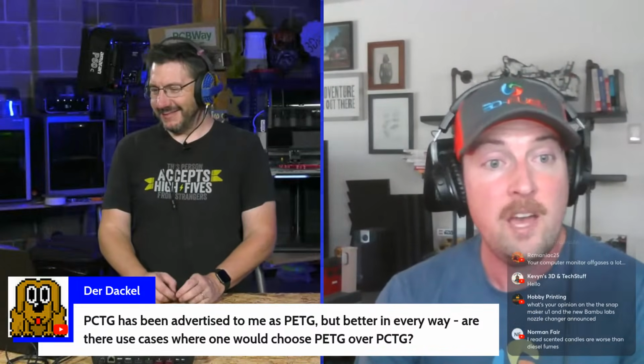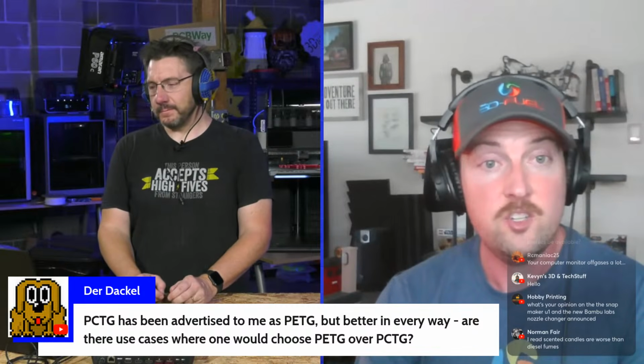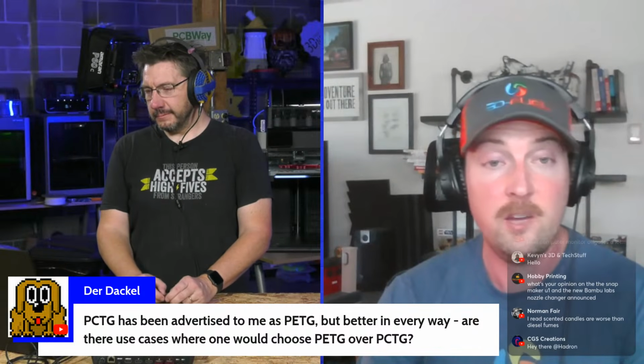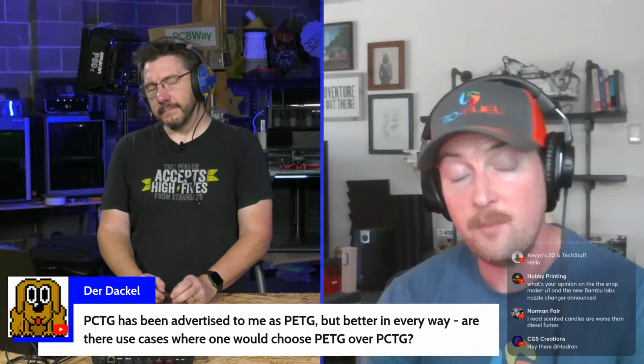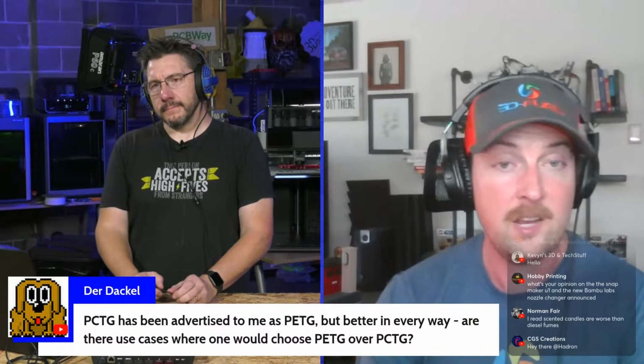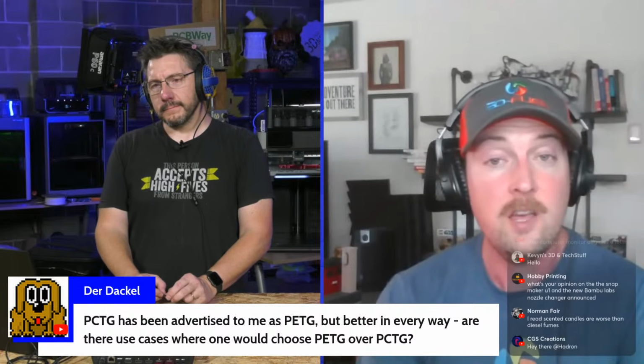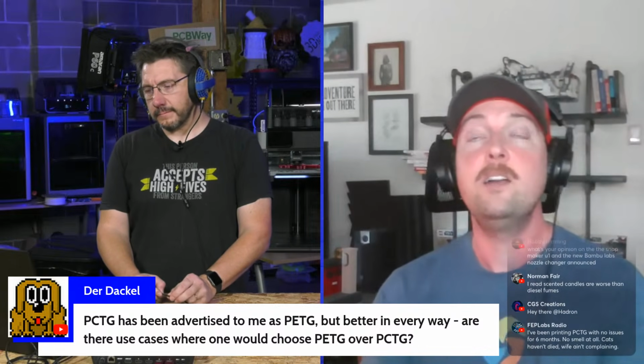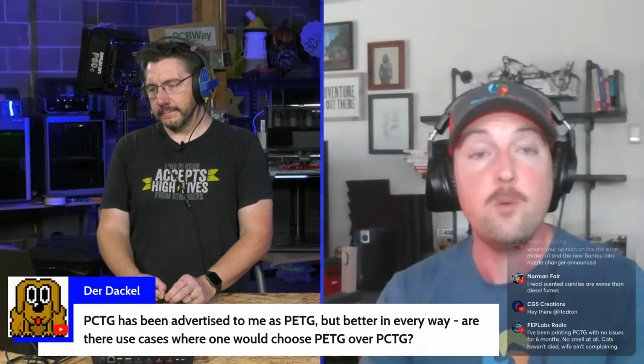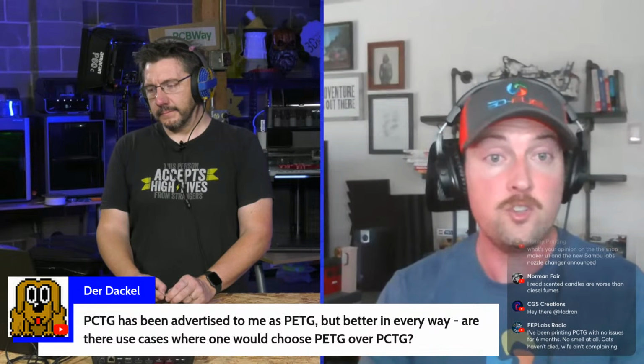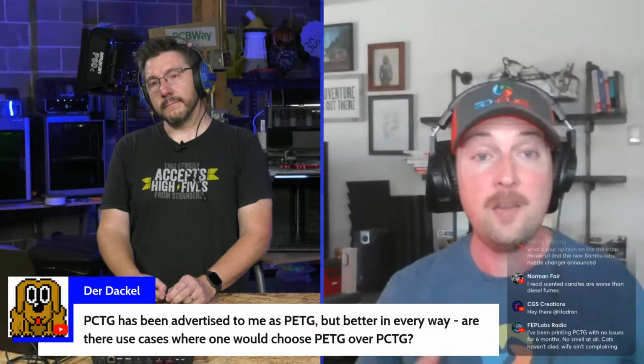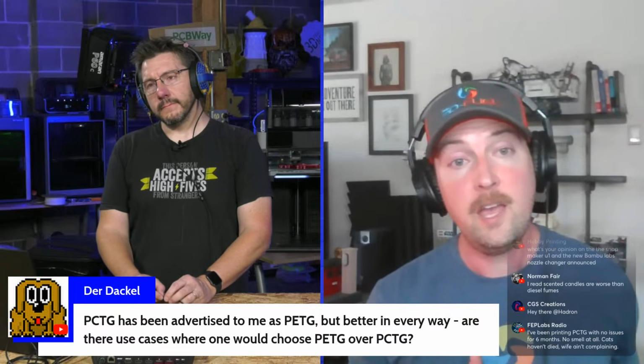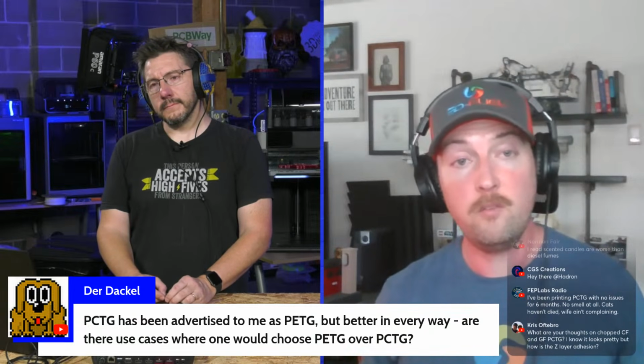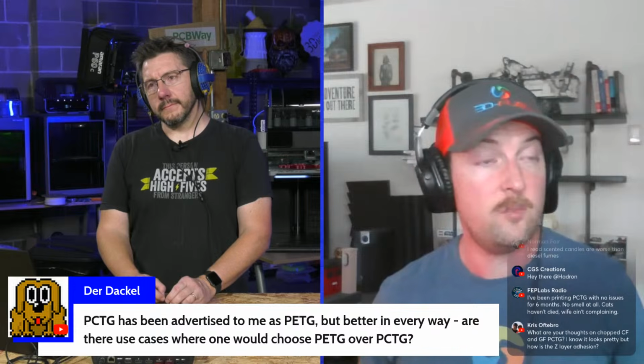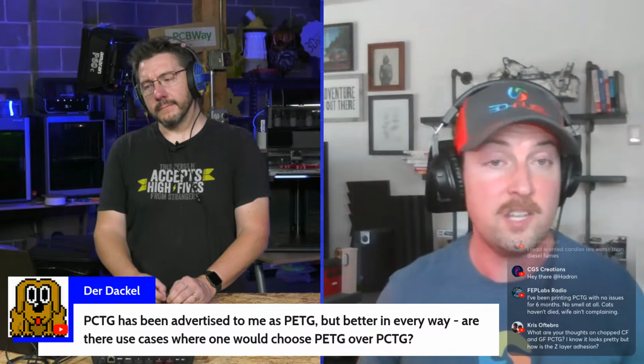And once we had more customers using PCTG, they're saying, man, I'm having a tough time with bed adhesion. The print keeps coming off the bed, or it shifts slightly, and I'm getting layer shifts. And what it came down to was that they were printing in a cooler environment than our shop is. So their overall ambient temperature was lower. And so what was working well for us in our environment, where it's maybe 75 degrees